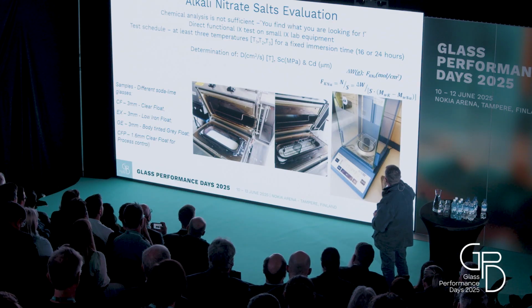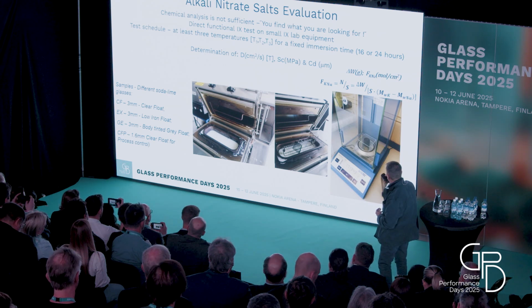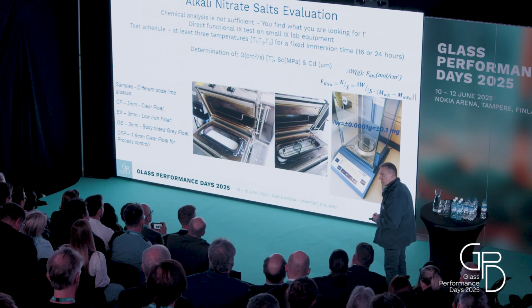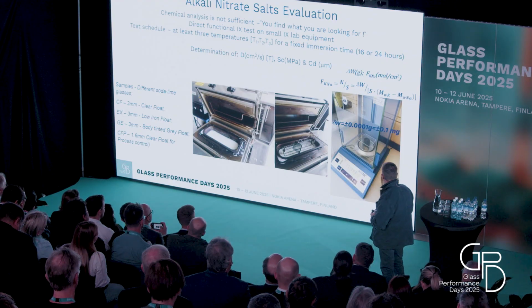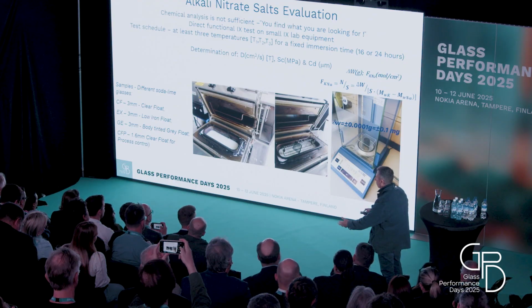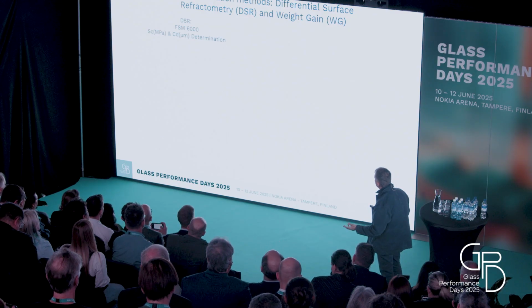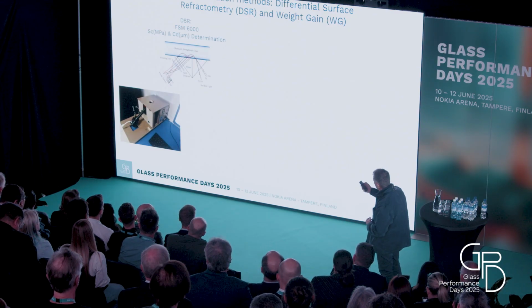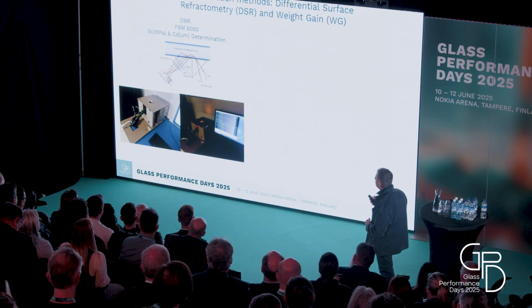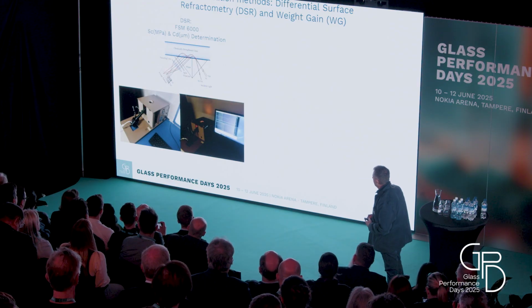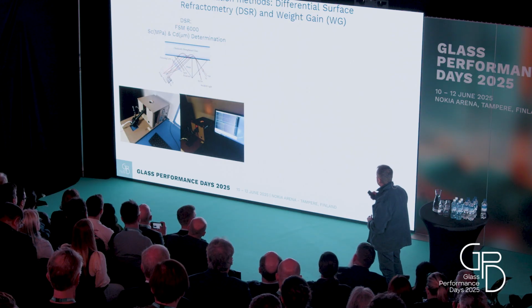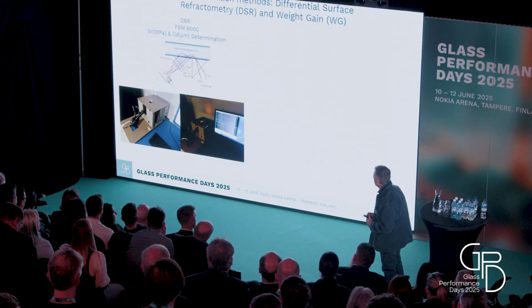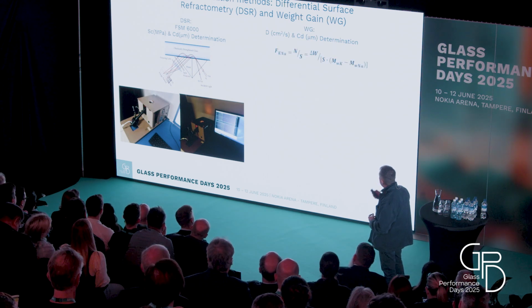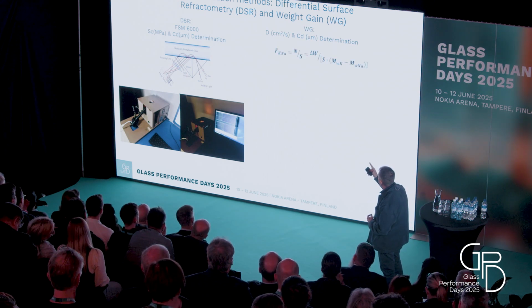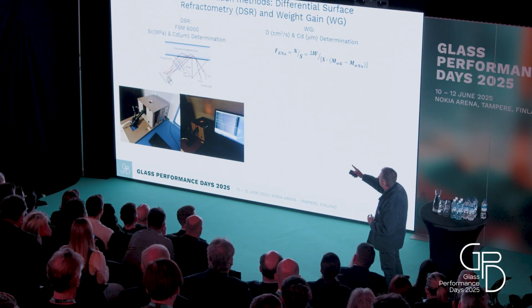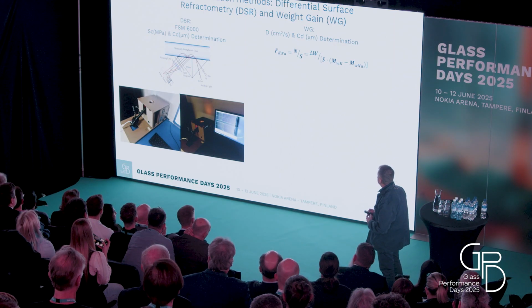You can use a weight gain technique using a balance like that, but be careful, it is not easy to do. That means that you have to use an analytical balance, not a normal balance. And for the characterization method, this is one possibility. The other one is by measuring the surface compression and the depth of compression. This is a differential surface refractometry that provides you this information. It is a non-contact method of measuring weight gain. So by weight gain, you have D, the interdiffusion coefficient, and the case depth, while with the other one, you have surface compression and case depth.